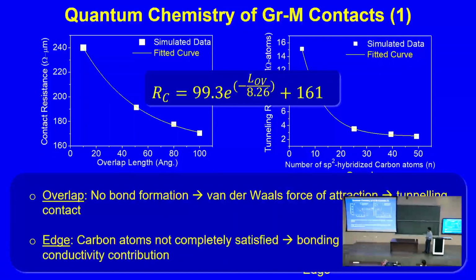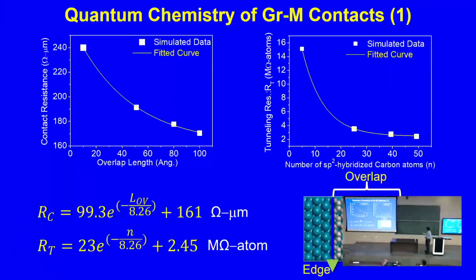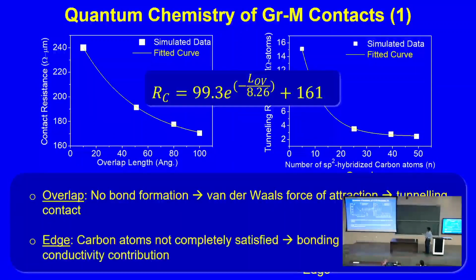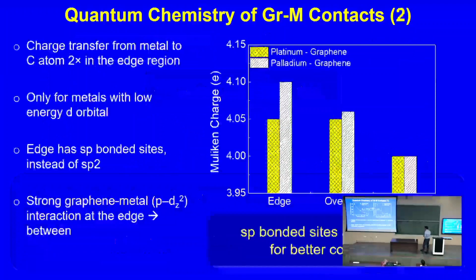And in the edge, we found that since these carbon atoms were not completely satisfied, the hybridized state was not sp2, it was actually sp. We found that there was a bonding channel formed. So there was a further hybridization of carbon and metal, and that formed another hybridized state, an sp-d hybridized state, which resulted in a bonding channel and 40% conduction from the edges. Now that gave us an idea of edge conduction and what the role of the edge is in these conducting channels.